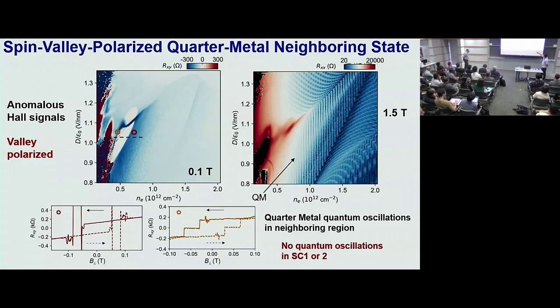It feels like if you just look at the superconductivity, there should be a big oval that's superconducting, and then it's cut through by the phase boundary between quarter metal and PIP. So I'm less confident about what SC2 is, although I think it's still valley polarized and it has to be FFLO, because even if it's one big K pocket and slightly smaller K prime pocket, you do have finite momentum for the Cooper pairs. But SC1 is more clear in that sense.